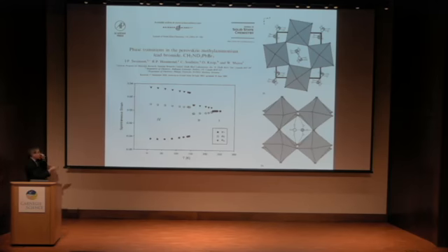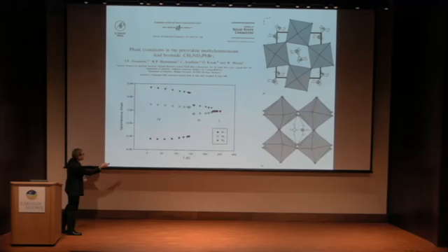And this system actually goes through three structural phase transitions, which are plotted here. So this is a plot of spontaneous strain versus temperature, done with neutron diffraction. At low temperatures, it has an orthorhombic unit cell. Then at around 150 Kelvin, it goes into a tetragonal phase. And finally, at high temperatures, it goes into a cubic unit cell up here.